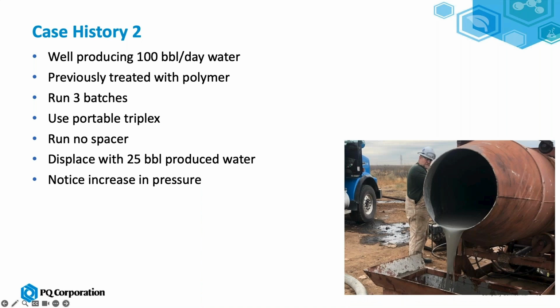So after that, it moved to this trial and others. In this case, the well was producing 100 barrels a day of water. It had been treated with a polymer-based system, so the operator was thinking to try to near wellbore pump in this material. So once again, want something that was very fine, that could be squeezed in. Small batch sizes, so it was run 3 batches made and then pumped using a portable triplex. In front of it, there was no spacer, and then it was displaced with 25 barrels of produced water. There was an increase in pressure as we're pumping, so we noticed that it was blocking off as it was going. And the operator did see a reduction in water. Next slide.